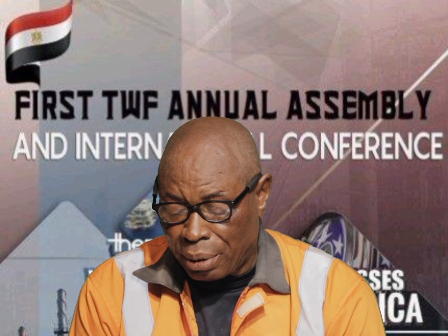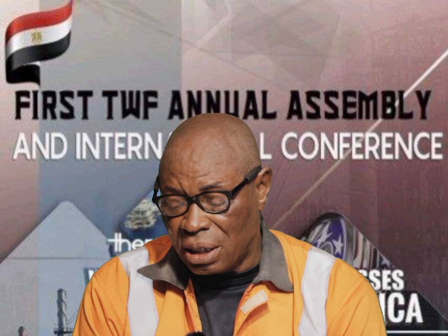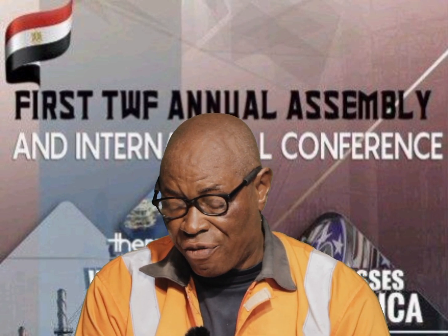Torch brazing: the flux is applied to the part surface, and a torch is used to direct the flame against the work in the vicinity of the joint. After the joint area of the work part has been heated to a suitable temperature, a filler metal, usually in wire or rod form, is added to the joint. Fuels used in torch brazing include acetylene, propane, butane, and other gases, with air or oxygen. Torch brazing is often performed manually, and skilled workers must be employed.